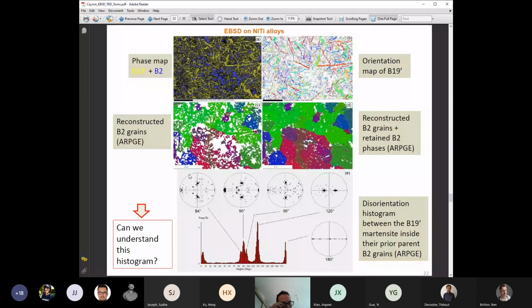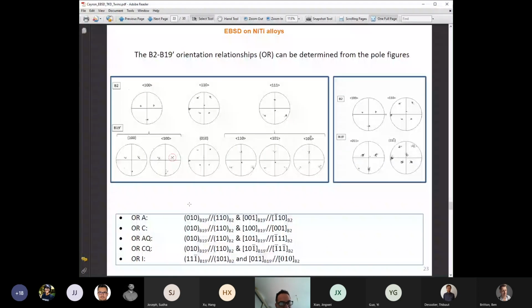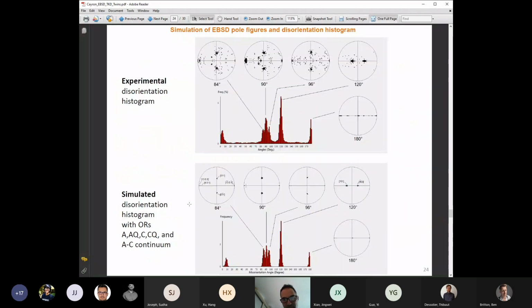First of all, you need to identify the orientation relationship between your cubic parent phase, the B2 phase, and the monoclinic phase, the martensite. Here, I was lucky because there is some retained B2 phase. So you look at the pole figures of B2 and of B19 prime phase, you look at the low index directions or planes, and you try to establish where there is a parallelism of the directions. It's quite fastidious, but if you do that, you realize that there is not a unique orientation relationship, but many of them. And if you take all of them into account, you can reproduce quite nicely the misorientation histograms.